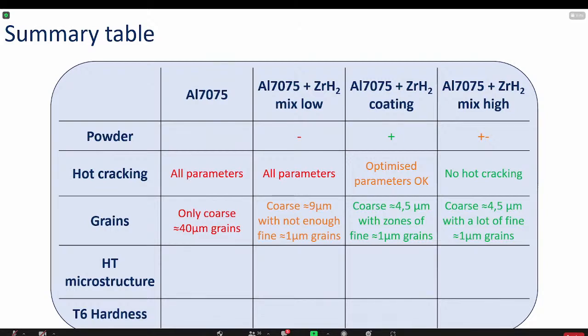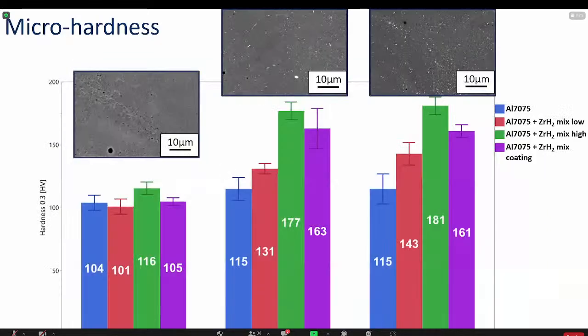And I have also analyzed the effect of a classical T6 heat treatment on these four powders. So the T6 treatment for the 7075 is 1 hour at 480 degrees of solution heat treatment, followed by 24 hours at 120 degrees. And what I have observed regarding the microstructure and the microhardness is that the difference between the complete T6 heat treatment and only the solution heat treatment is really low. There is not much difference in the microstructure, and the hardness is roughly the same for the different alloys.